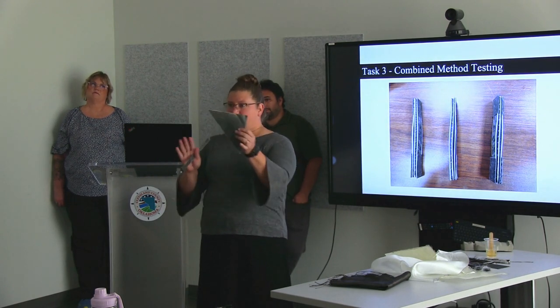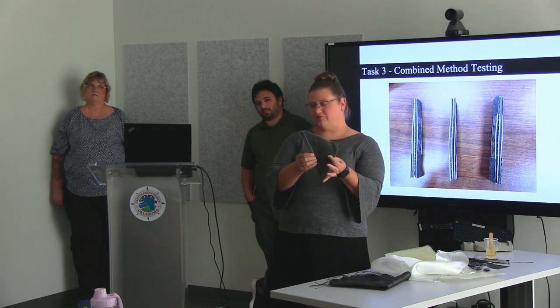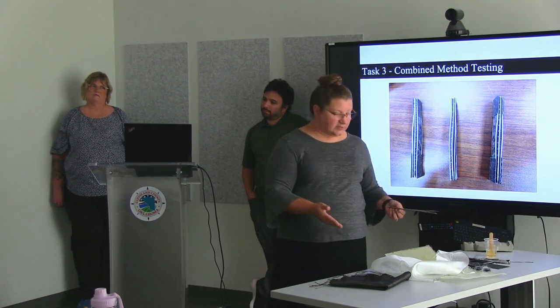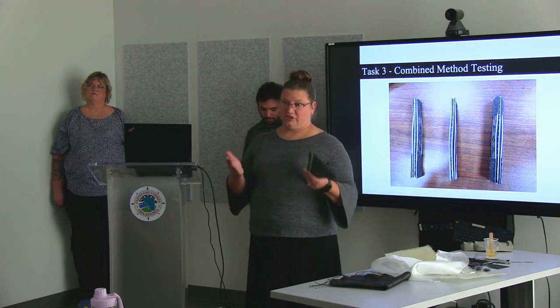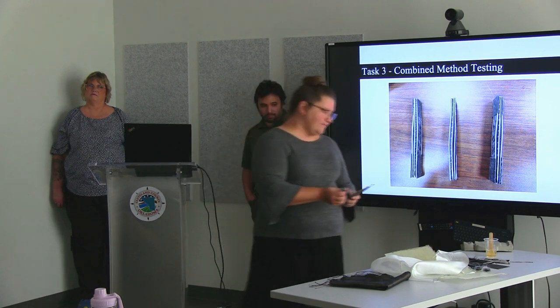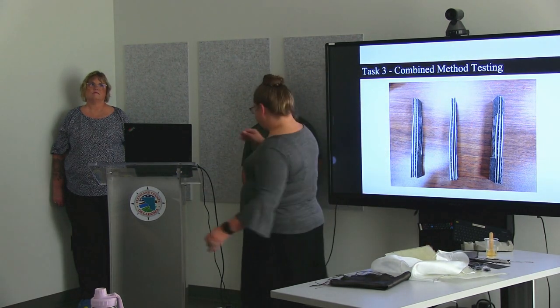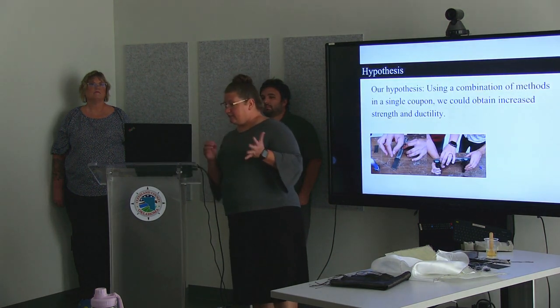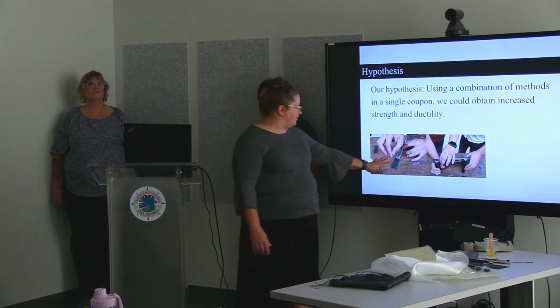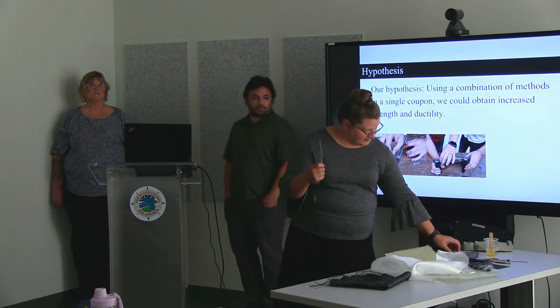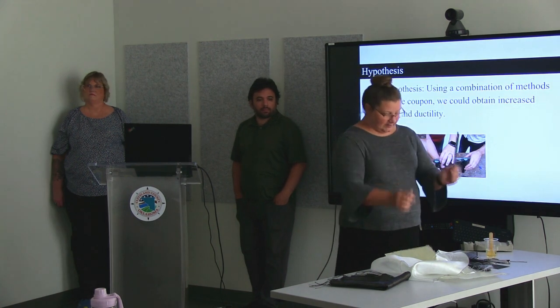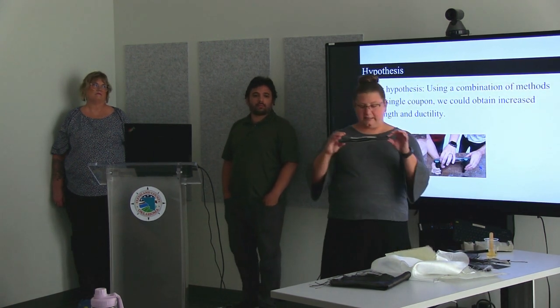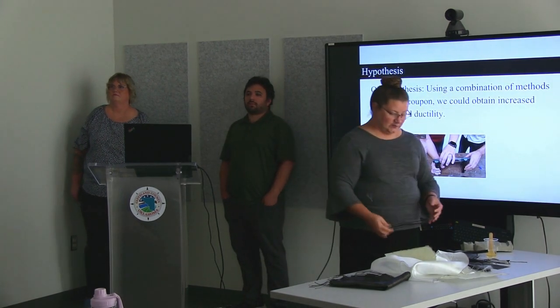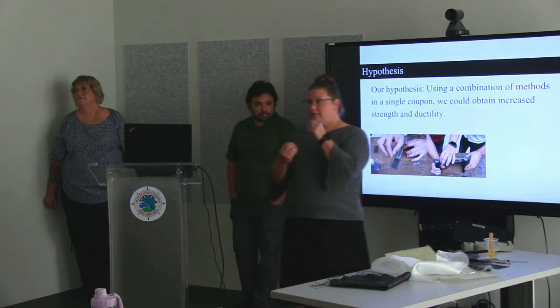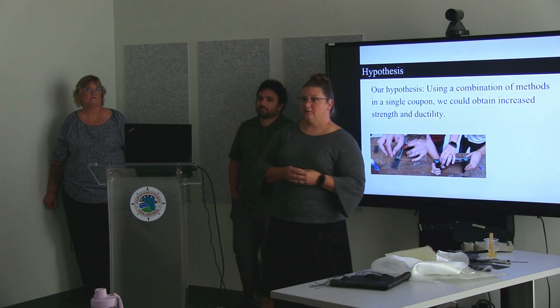So we got our protractor out, our nice, pretty straight cuts. Again, when you're working with the fiber and you're applying epoxy, it does have a tendency to shift, which can affect your angle measures. So our combined method, we had a lot of layers. This is a picture of us with our separate pieces, putting them together. So we had our 3D printed pieces in between our wet layup pieces to give us some very, very thick coupons, which we then attached our tabs to so that the machine could hold on to it when it was tensile stress testing.